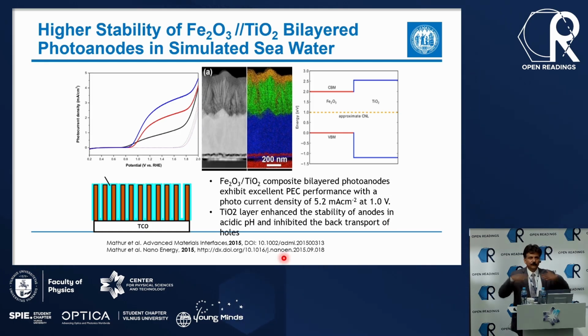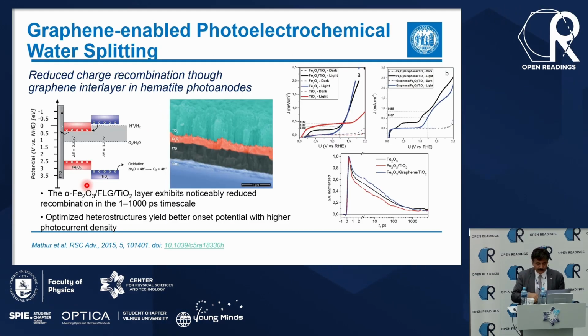Then we realized that by using this combination of iron oxide and titanium oxide, where titanium oxide is your capping layer, which is absorbing UV light, and then you have beneath it iron oxide, which is absorbing visible light. And this combination gives you a very good photoelectrocatalyst. The problem is, as I said, they are not very good conductors, so at the interface, you will have a lot of charge accumulation. So here we use graphene. You can just put a small layer. You don't see, obviously, a single layer of graphene between iron oxide and your substrate, and you can increase the water splitting. So this is something that works.